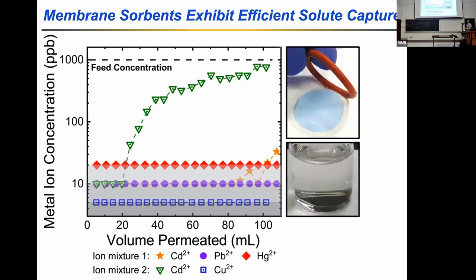But the last thing I'll say about this is in that bottom experiment with the cadmium and copper, that 1 part per million feed solution is completely clear. After treating 100 milliliters of that feed solution, the membrane top surface has now turned this brilliant blue color because of all the copper ions that have been fixed on the surface. Right, so just another indication of its strong performance.